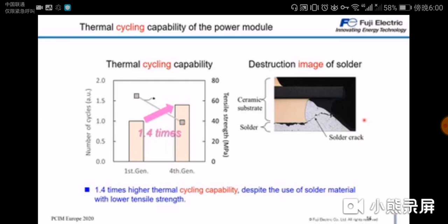On the right side we can see a typical destruction image of a thermal cycle. If you have a lot of thermal cycles, the solder crack will start here at the outside of the connection and then move inwards, thus increasing the thermal resistance even more.